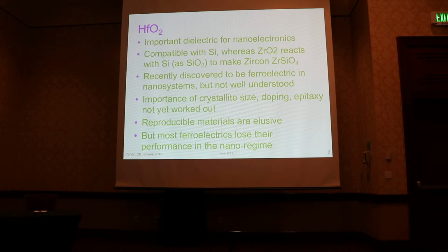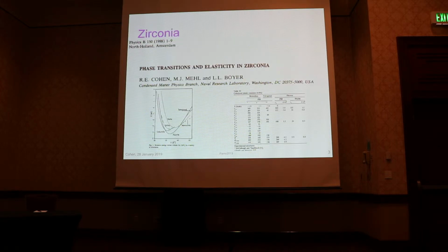In the experiments, it's also not very reproducible. So there's a lot of questions about what's going on in the system, and I'll show some of that in this short talk. Most ferroelectrics lose their performance as ferroelectrics in the nano regime, and that's another reason that this is such an important material, because it seems to work better in nano form than it does in bulk. In bulk, it's not ferroelectric at all.